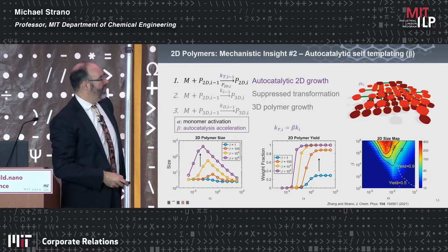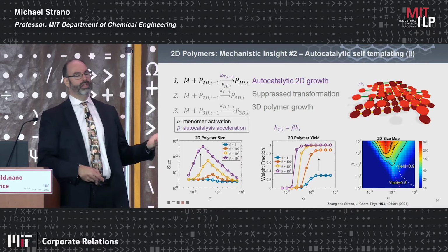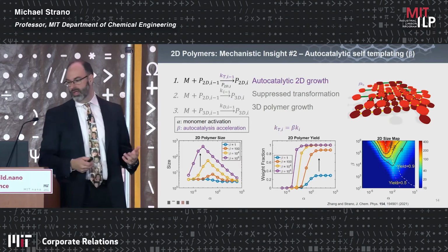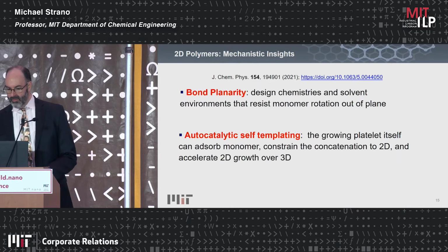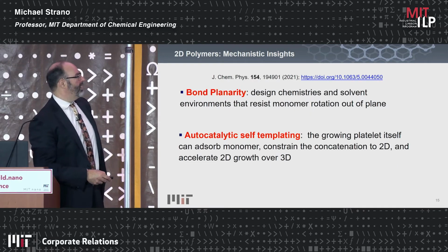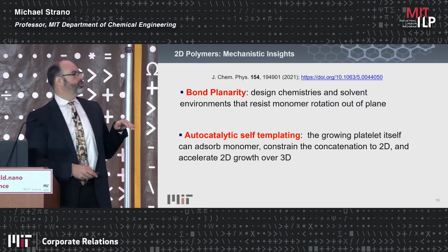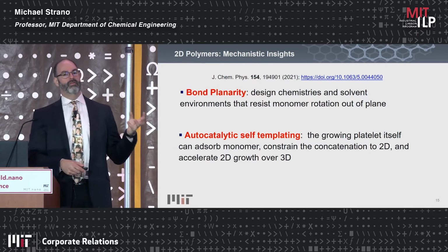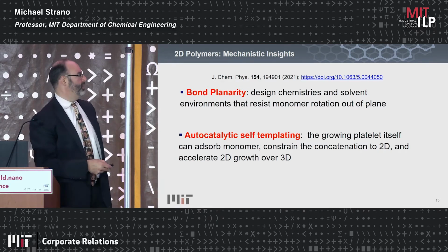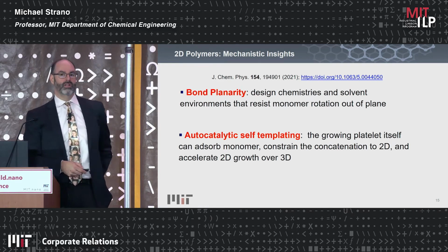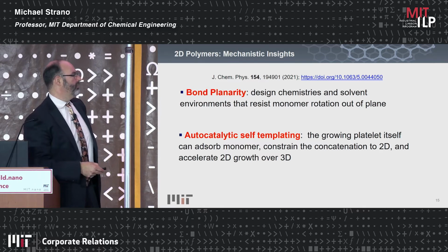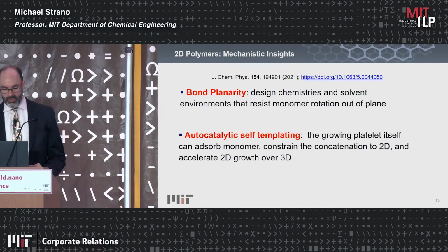And I'll show you here, these are parameters related to the polymerization. This is the extent to which you can get that templating to occur. And this is the polymer initiation rate. And you're supposed to see that there's an island here, a sweet spot, a Goldilocks spot, where if you can get into this synthetic range, you can make these 2-dimensional polymers. So there are actually two mechanisms. One is you can try to use chemistries that will keep the bond planar, but we don't have complete control over the periodic table and organic chemistry. We have to inherit that. But this autocatalytic templating comes right from nanotechnology. And it's a potentially very general mechanistic pathway that can grow materials in this 2-dimensional configuration.